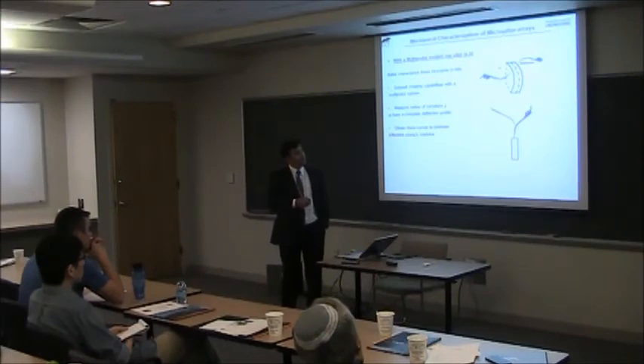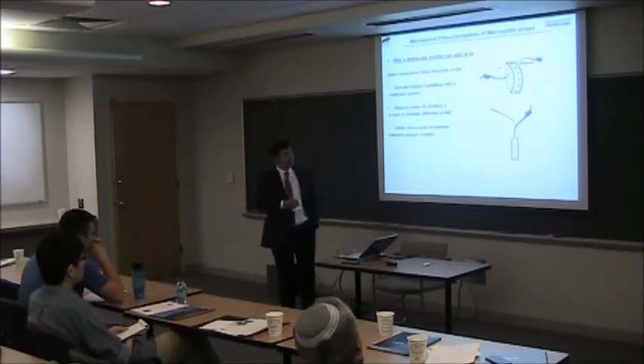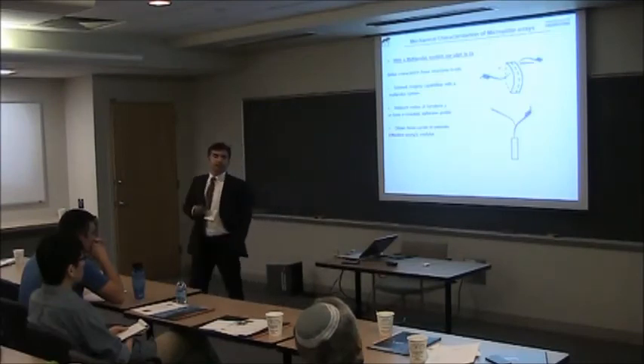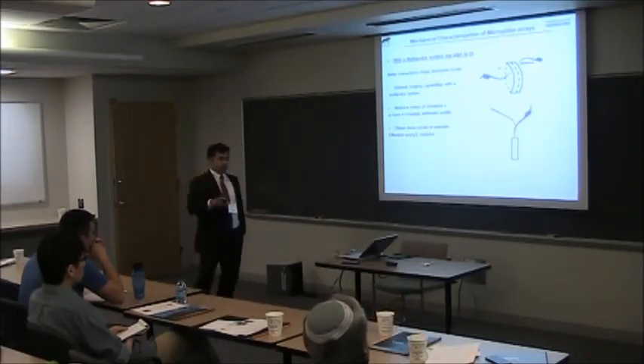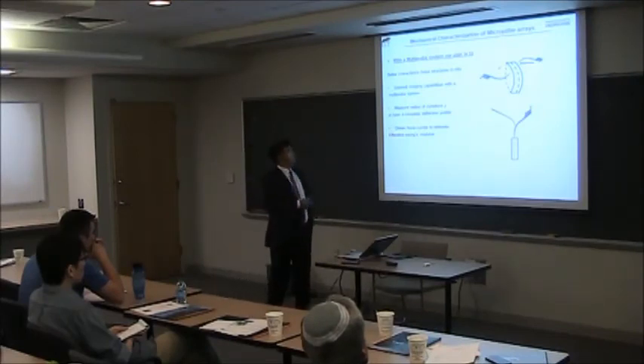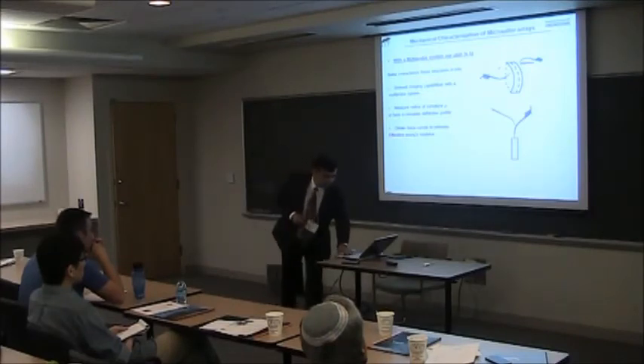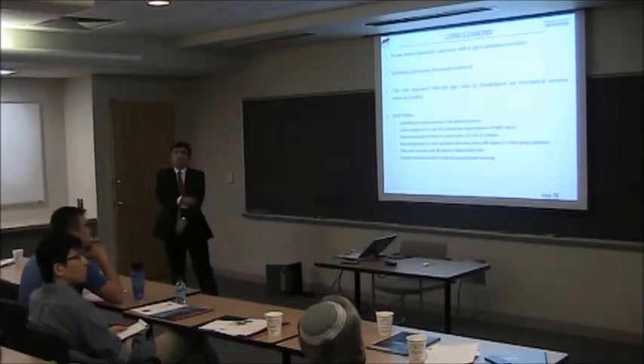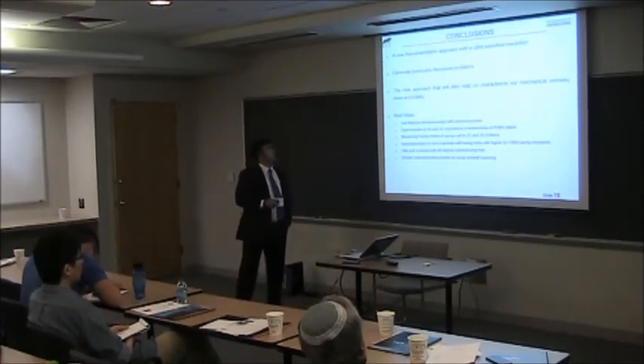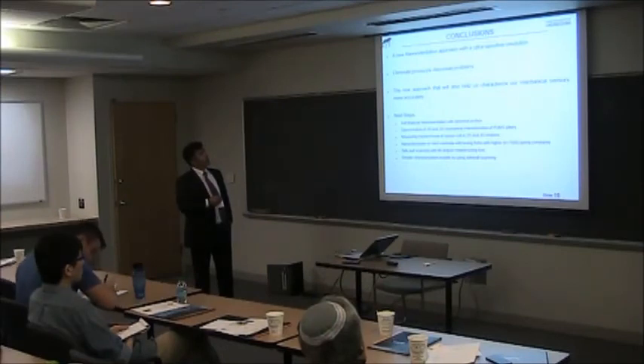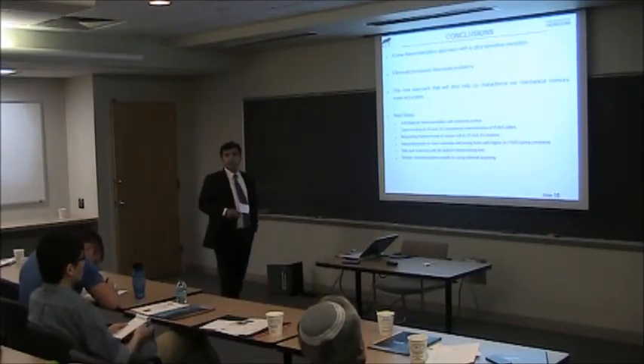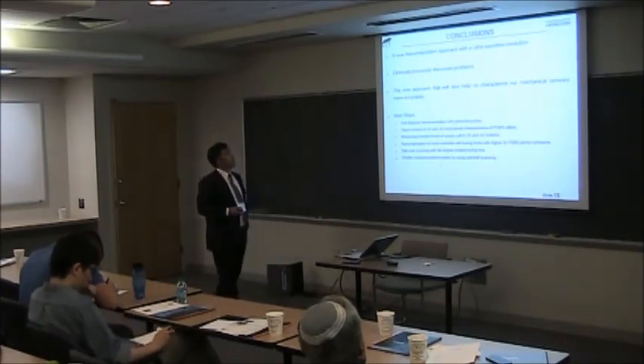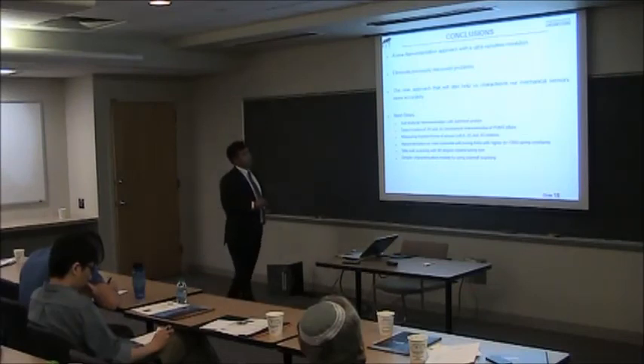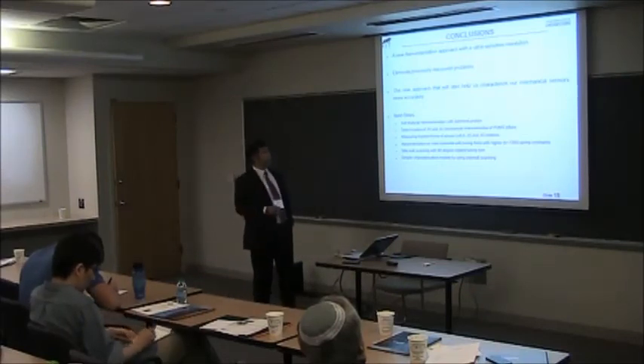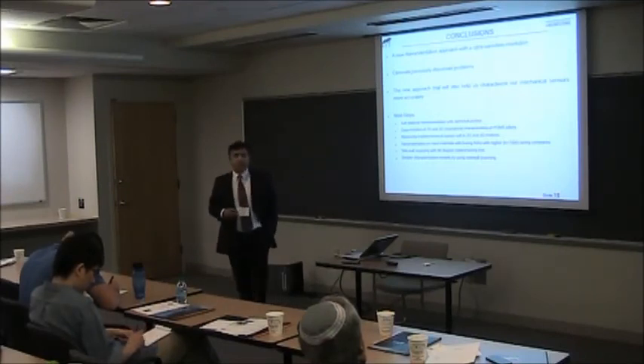Can we actually take a probe and put it on top of the pillar, push it down with a very, very small indentation, and then measure with the second probe and do the same calculations, instead of a thin film or film structure of PDMS? This is basically our next step after we complete the silicon nanoindentation and get the forces completely clean, with ultra-sensitive resolution, measuring very small, piconewton-level forces. We are hoping to do the same thing with spherical probes on PDMS, just thin films first, and then go to 2D and 3D mechanical characterization of PDMS.